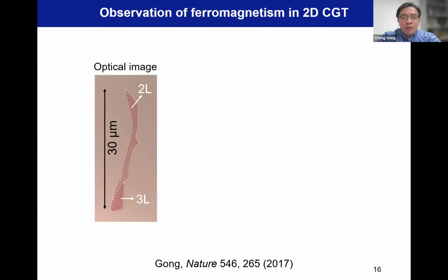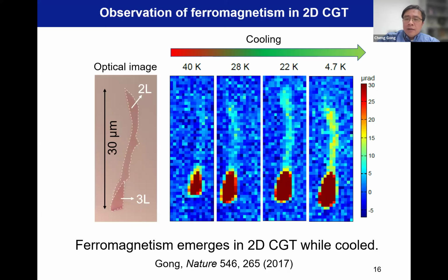And this is the optical image of the two and three layer chromium germanium telluride I exfoliated before on a silicon oxide silicon chip. When we put it in a cryostat and cool it down, at low temperature, around 4 Kelvin, you can see a clear emergence of Kerr rotation angle. But at 40K, at a slightly elevated temperature, the two layer sample's Kerr rotation signal is gone, but the three layer is still there, quite robust. That indicates a strong thickness dependent TC.